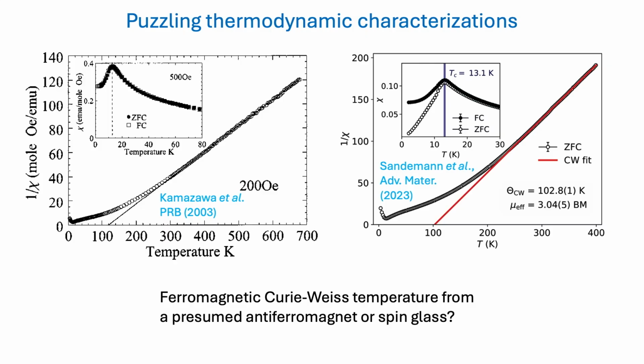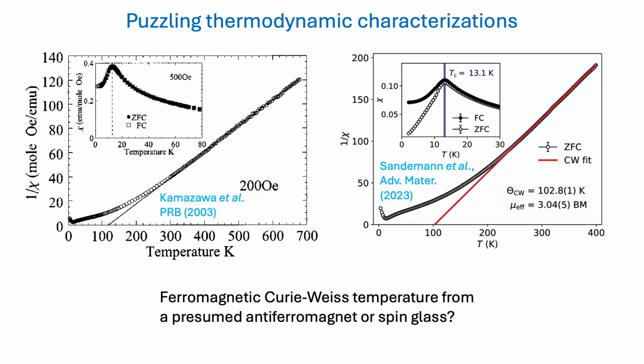What he means is that if you measure the magnetic susceptibility of the system and plot the inverse of the magnetic susceptibility against the temperature, you can fit the data with a so-called Curie-Weiss plot with a straight line. And the intercept tells you whether this is a ferromagnetic or antiferromagnetic system. A positive value is a ferromagnetic system. However, if you look at the susceptibility itself, it is typically an antiferromagnetic system. So the puzzle for Anderson and for everyone else is: how do you have a ferromagnetic interaction dominated system have an antiferromagnetic phase?